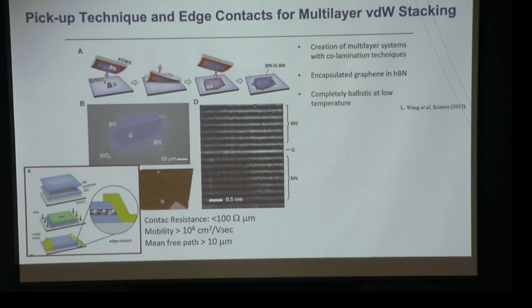And graphene, which consists of just a single layer of carbon atoms, has fewer defects once grown into really improved conditions. Encapsulation with boron nitride, which is a good crystal, immediately boosts the quality of the sample, such that electrons can travel about 10 or 100 microns before meeting defects or the sample edges and scattering. Such high quality and large mobility immediately allows us to study interesting quantum physics.